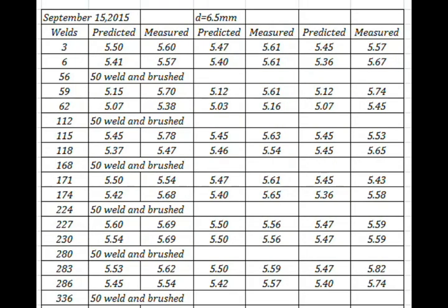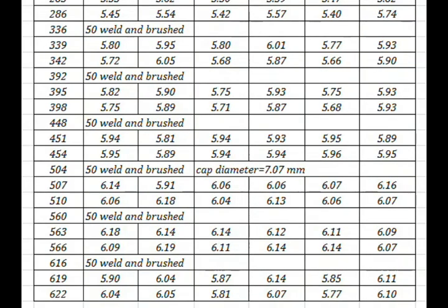12 years after I welded my first weld, I finally was able to close the loop to weld constant temperature welds. I programmed the temperature at about 850 degrees Celsius, which was 10.0 kiloamperes, 200 milliseconds with a 6.5 mm B cap. The force used is 500 pounds. After welding 2 coupons or 6 welds, I welded 50 welds on 2 10-inch by 12-inch sheets. At that time I also cleaned the cap surface with a wire brush to get rid of zinc deposit.